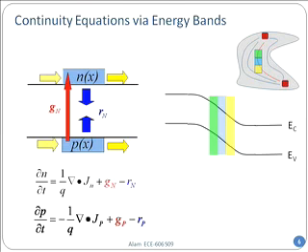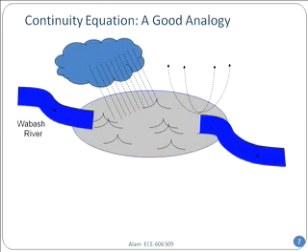you should convince yourself that the net rate should be independent of the current that is flowing in, because no net number of electrons can change. Holes have been created, that means electrons have been pumped up, but that does not change the total number of electrons. When something got recombined, an electron was in the conduction band that came down to the valence band. But if you look at the material as a whole, of course, electron and hole remains the same, no problem. Individual components can change easily, electron and hole number, but not the global number. It's a very important thing to remember.